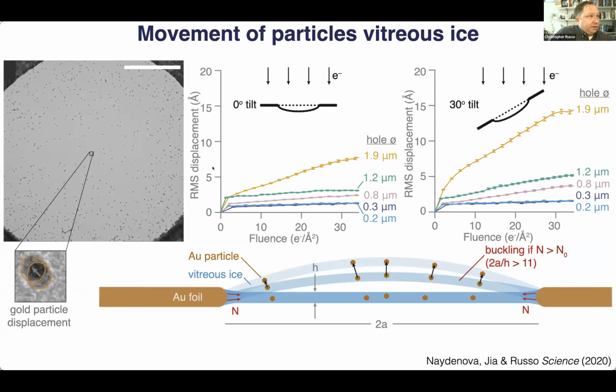And that was to say that by reducing the size of the hole that the ice layer is suspended across, the movement is reduced. But actually, after the hole was reduced to below a size of about 0.3 microns, 300 nanometers, there was no further reduction in the movement of the particles. So there was actually a threshold effect. So once one made a hole that was small enough, eventually the particles stopped moving entirely. And if you kept making the hole size smaller and smaller, it didn't change the movement of the particles anymore.